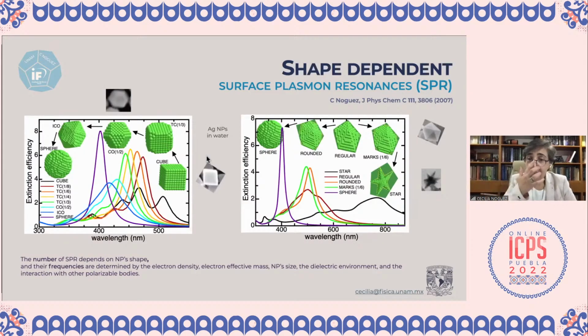As I said, the number of resonances and the frequency of the resonances will depend on the shape of the nanoparticle. For example, in this case, we can start with a sphere. For a sphere, we have only one resonance. That depends, as I showed you, on how homogeneously the charges are distributed around the sphere. So you have a single resonance for the sphere, this one that I'm showing here, this purple line.